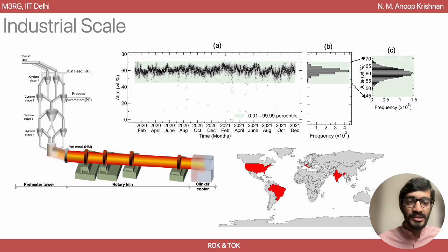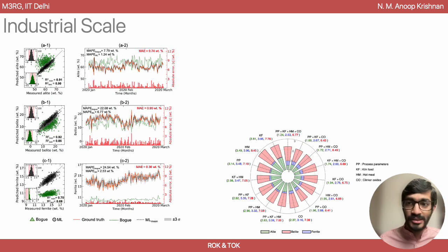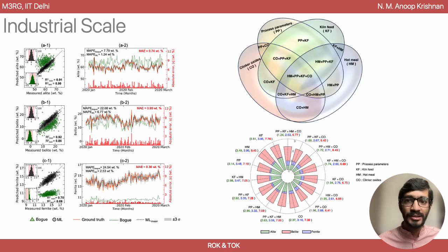So here is the alite weight percentage produced as a function of 2 years, right? And you can see it's a fairly Gaussian distribution. So what we did was we took all of this data and all the process parameters, which is around 70 process parameters, and then tried to predict alite, belite and ferrite phases. And we did this with different combinations. Okay, what are the different combinations we considered? We predicted it only using process parameters. We used it with process parameters and kiln feed, hot meal, process parameters and kiln feed, and with clinker oxide.